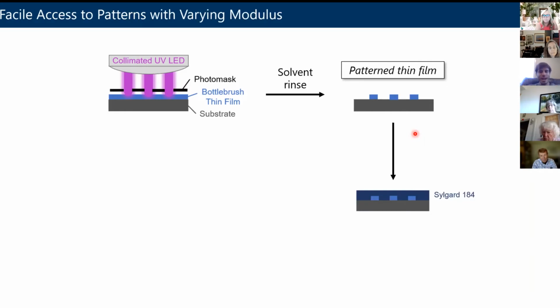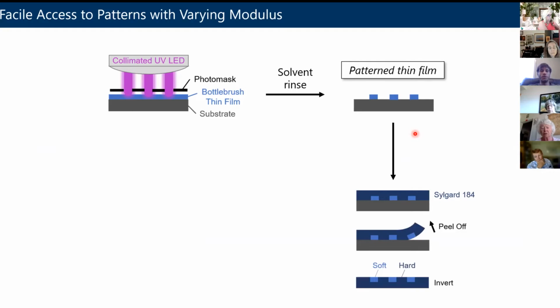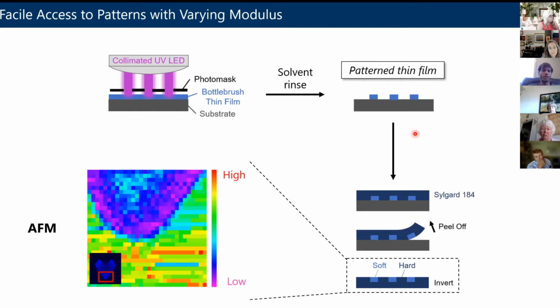And you can create flat patterns where you control how stiff is the material. For example, by backfilling with your linear Sylgard 184, curing it, and then peeling it off the substrate, which brings along the super soft elastomer regions as well. So now you've got a flat object that has really super soft and harder regions, depending on the photomask you used in different shapes and patterns. You can image this with a different technique called atomic force microscopy, which we have available on campus, where the color now corresponds with how soft or how stiff is the region of the surface. So you can see this is a zoom in of a heart region. It's blue, which means it's much softer. Everything else is more green. It's much stiffer.